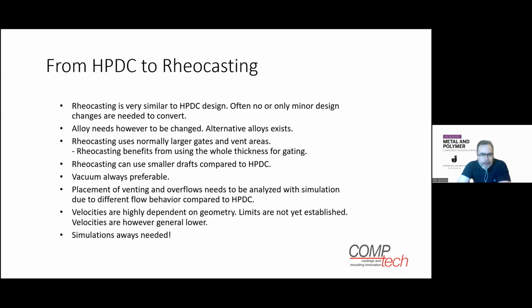If we take thin wall into Rheocasting, it's more similar to conventional high pressure die casting design. Often only very small or minor design changes need to be made. The alloy, however, needs to be changed, and there are alternative alloys that exist. We normally use larger gates and vent areas, which means you might have a change in how you remove the gates. You use perhaps conventional trim pressing, and that may have to be changed into some kind of cutting solution instead.